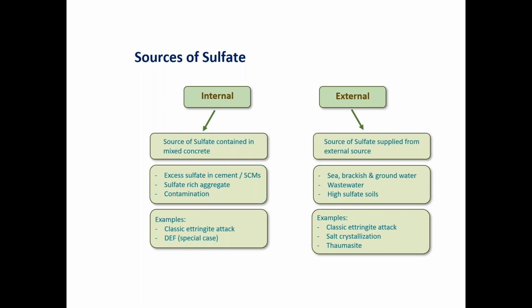If you're familiar with the process of producing cement, calcium sulfate is added in the milling stage with clinker and other additives to help restrain the aluminate phases of cement from taking over and creating adverse effects, things like false setting, flash setting. But when these things are incorporated in high amounts, and again, I really wasn't able to find a lot of documentation of this happening, but I would assume it has to be in very extreme amounts, again, with the exception of delayed ettringite formation, that you can essentially build in the sulfate source.